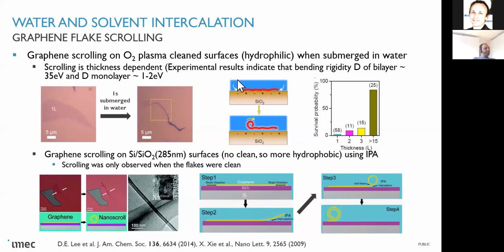The final problem that I would like to just briefly touch with you is the problem of adhesion, and mainly of intercalation effects that we see. So if your surface is hydrophilic and you put your 2D material in any kind of aqueous ambient, what you will have is that water will intercalate very fast at the surface. If you have only like a monolayer there, it can induce a kind of scrolling up mechanism, and you will find these kind of scrolled graphene here.